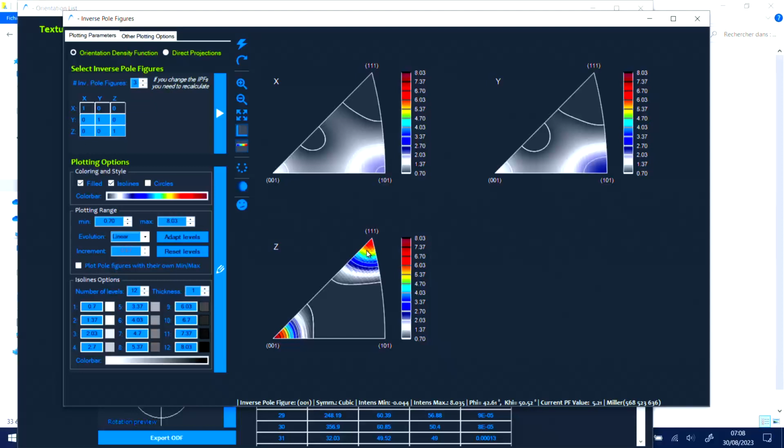Here the texture changes are visible easily, but in hexagonal, if there is twinning, it's even more spectacular. It can be very spectacular. Small strain and completely different texture. So that kind of calculation I would also like to do as a simulation with you, so that you see what further possibilities there are in terms of simulation work. Any question on this part?